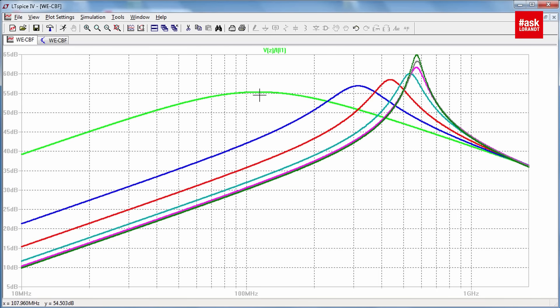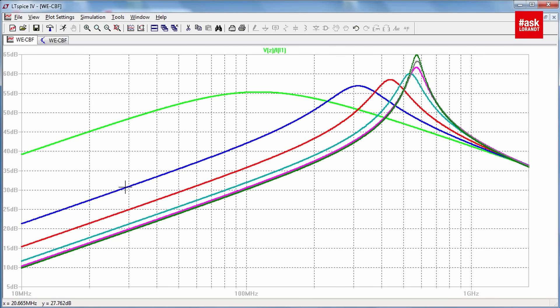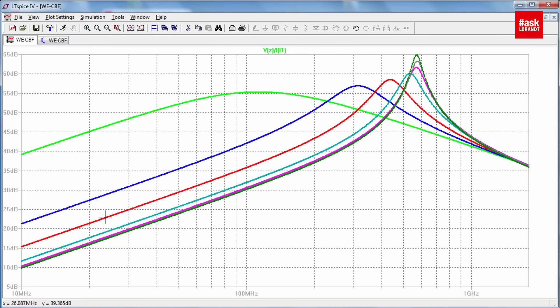The green curve is what you have also in Red Expert with zero DC bias load. This is actually in all data sheets - it is measured in 50 ohm system impedance with zero DC bias load. If you apply to this ferrite bead 500 milliamp DC bias load from pre-magnetization it will happen that the impedance or the attenuation will drop a lot and this is the blue curve here.